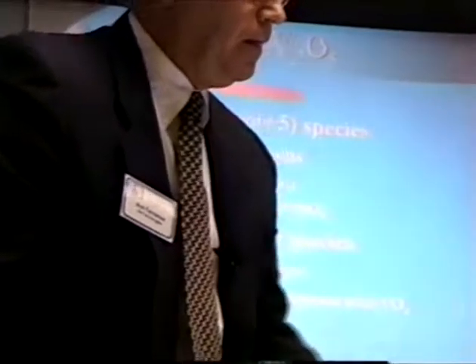Once you've done an impregnation on a support, what do you have? Some surface niobium 5 species. Niobium is very difficult to reduce. It's essentially +5 and it doesn't change. These are monooxo units, isolated NbO4, and some polymerized NbO6 at higher loadings. In contrast, vanadium 5 is also monooxo, but there are VO4 units in the structure.